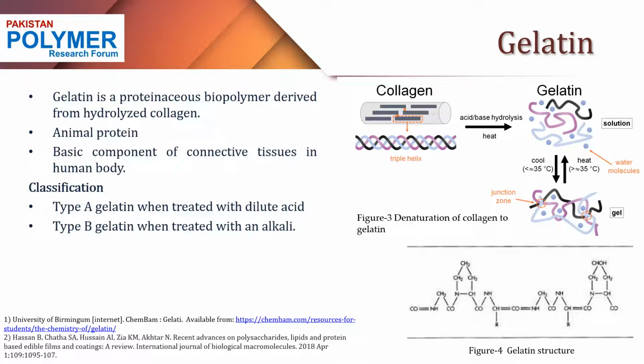For collagen to be soluble in water, we have to heat it and hydrolyze it in the presence of certain catalysts. What are the catalysts? Catalysts are acid based or base based. Depending on the catalyst, we classify gelatin into two types: type A gelatin and type B gelatin. If we use an acid-based hydrolysis process for the conversion of collagen to gelatin, this will be type A gelatin, and if we use a base hydrolysis process, this will be type B gelatin.